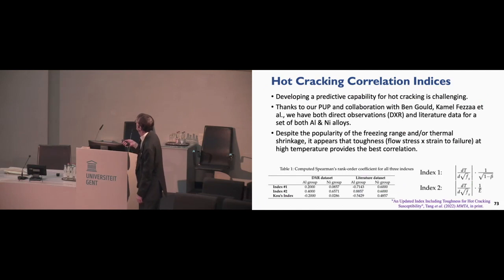And so when we looked at the competing indexes, the first of our indexes had the Scheil characteristic in it, if you like, plus an extra factor for shrinkage. And you can see that the correlation coefficients are really not very good from the synchrotron work, somewhat better for the literature data sets. But when we made a second index, that's the middle row, then we were able to get good correlation both with our own synchrotron experiments and with the data from the literature.